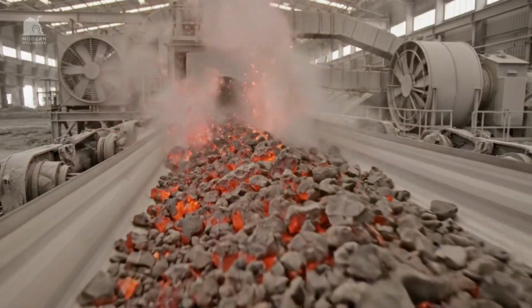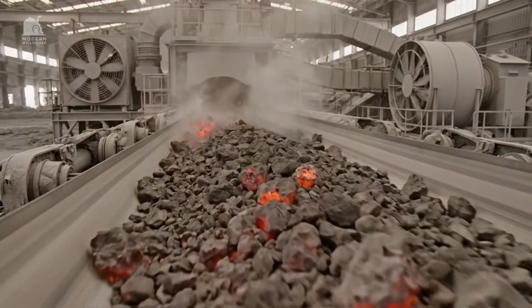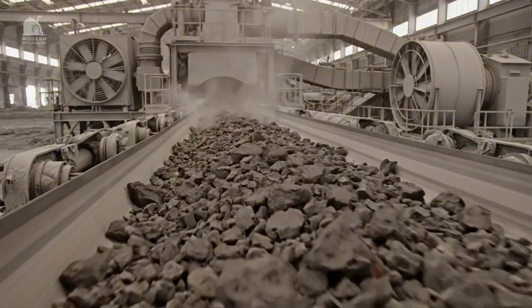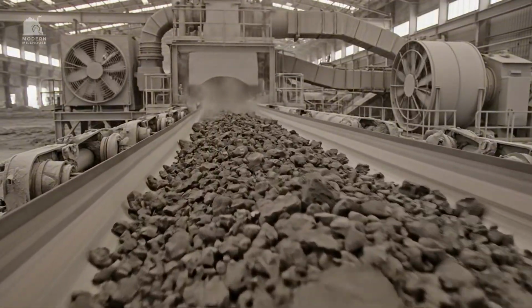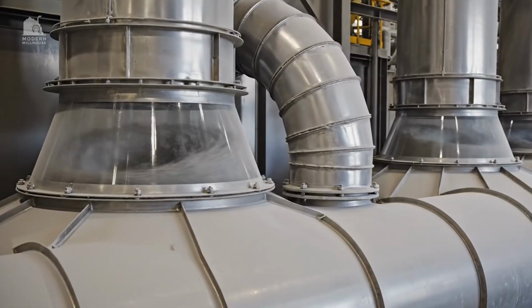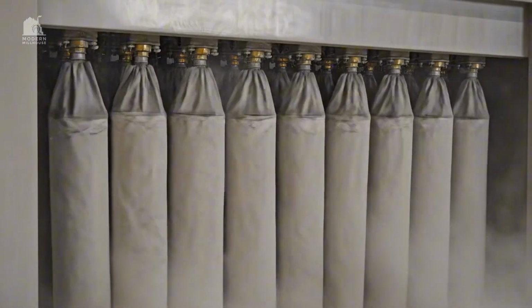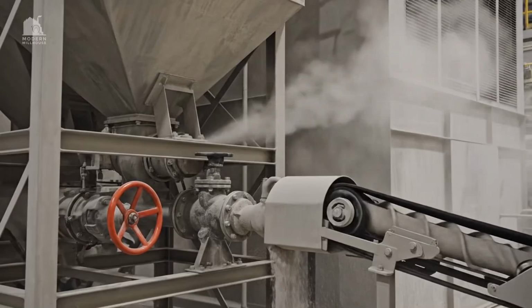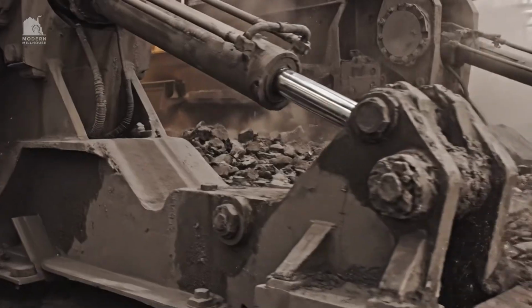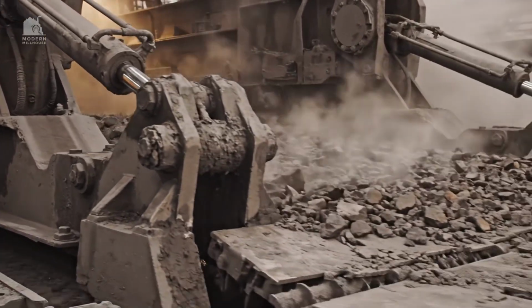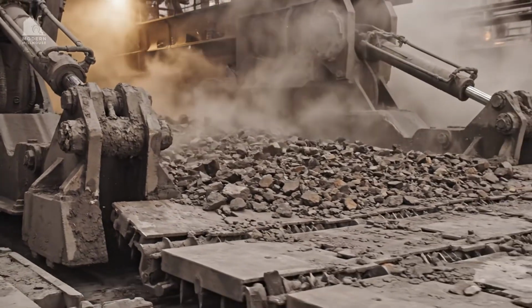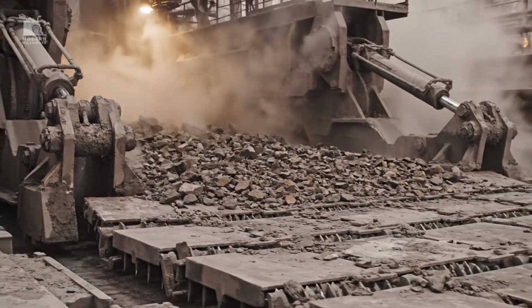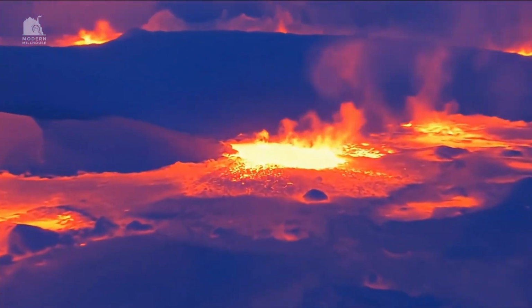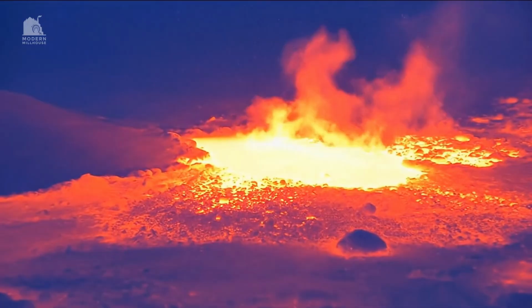After cooling, clinker becomes solid and manageable, but it still carries enough heat to require careful handling. Cooler exhaust is filtered to control dust, and collected fines are recycled rather than released to the atmosphere. Grate speed and airflow must match production rate, keeping cooling fast without grinding clinker into dust. Operators watch bed depth and temperature patterns because uneven cooling can affect clinker quality and downstream grinding.